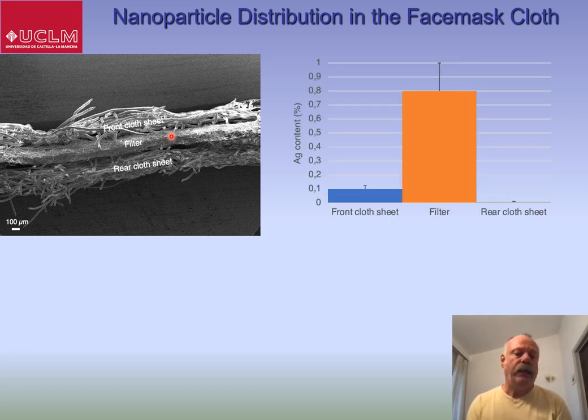Now, looking at EDX data for silver within the face mask, we find that a very small amount is coated on the front cloth sheet. The vast majority is coated in the filter with a virtually undetectable level of silver in the rear cloth sheet. So virtually all the silver nanoparticles are stopped within the filter.